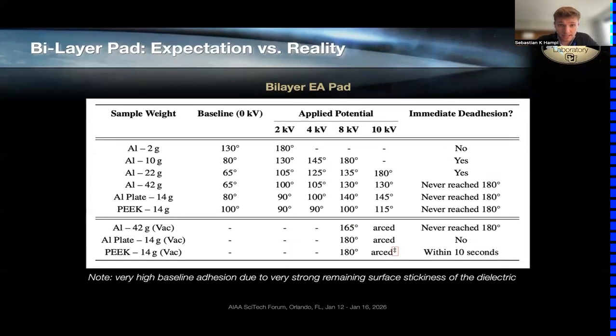Then we repeated those tests with the bilayer pad. And what's important to note is that the bilayer pad showed very high baseline stickiness just from the coating process, and the coating material was just sticky in general. So it is more difficult to directly compare these rotation results to the previous results. However, in general, the bilayer pad performed slightly less well than the other pad.